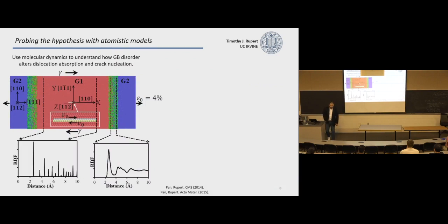I said we wanted to look at mechanisms. One way we could start to poke at this is by modeling what this process would look like. This looks funky, but it is a good way of emphasizing what we can do with atomistic modeling that can complement what we then will do actually making materials. In this case, I made a really simple type of model. I have 2 grains, so there's grain boundaries here and there in between. And in the middle of that inner grain, I'm going to operate a dislocation source. I'm going to kick dislocations in either direction.